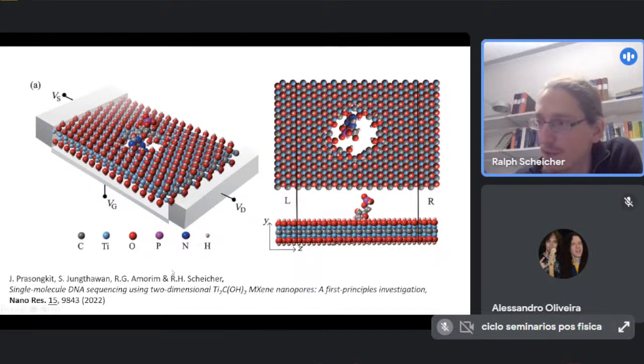And the last paper, one of the most recent works that we've done in the field of 2D materials for DNA sequencing, is with something called MXene materials. So they all have some characteristic chemical formula here. This one is titanium 3 carbon, and then it's functionalized here with hydroxyl groups. So basically, again, a similar setup. We have a source electrode, a drain electrode, and also a gate electrode. I didn't talk so much about this before, but basically the role of the gate electrode is to shift the Fermi level or the chemical potential of the entire 2D material to different points in the energy, and thereby can make the pore more sensitive.